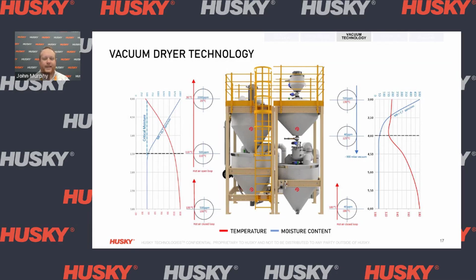In stage 1, we see a very similar situation as a desiccant-based dryer. We see the temperature increasing rapidly up to around 100 degrees Celsius, and we see a very stable linear line of moisture removal where we're able to remove that easy to remove outer moisture. At the end of stage 1, we do reach that critical moisture level where we have removed that outer moisture, but still have not removed the inner moisture.